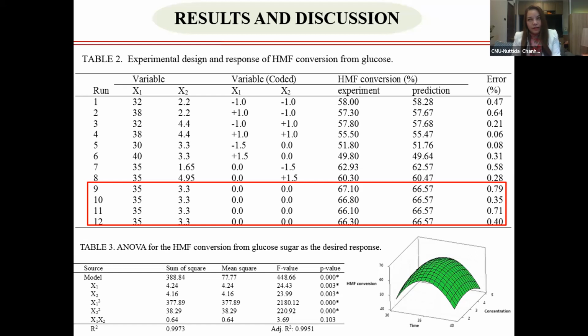I focus on the repetition of the experiment. It was found that conditions 9 to 12 gave HMF of 67.1, 66.8, 66.1 and 66.3% as experimental results. This can be compared with the simulation of the CCD technique, which gives a yield of HMF of 66.57% respectively.